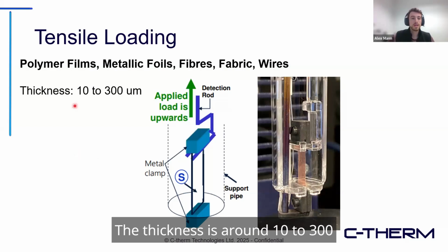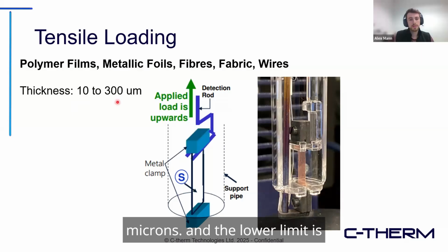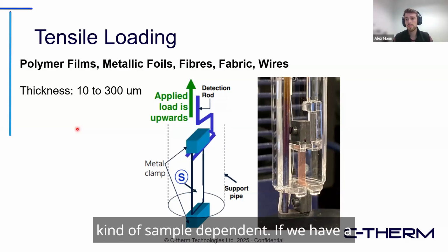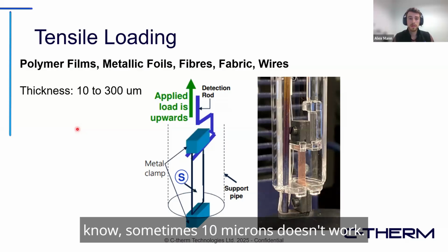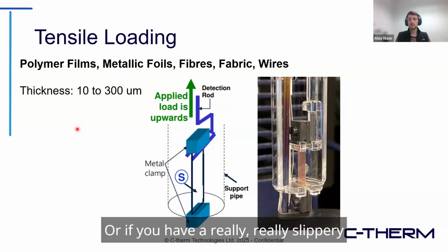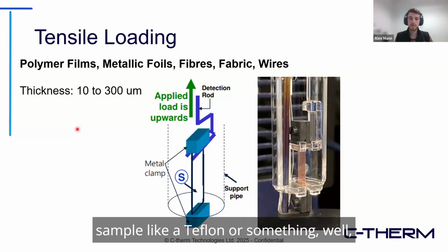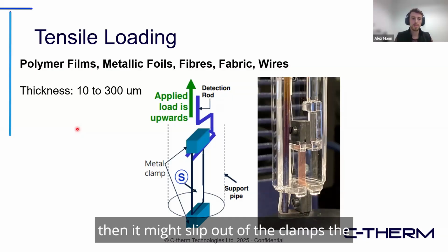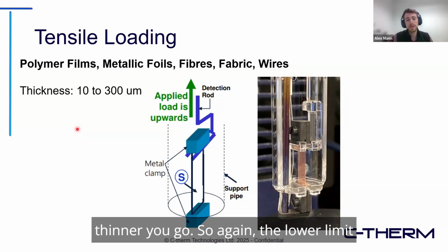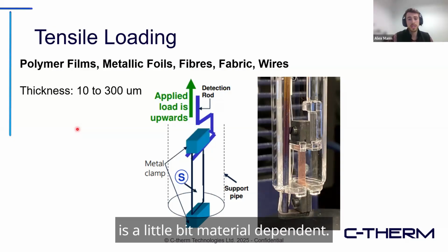The thickness is around 10 to 300 microns. And the lower limit is kind of sample dependent. If we have a very, very weak sample that can't withstand the clamping force, then sometimes 10 microns doesn't work. Or if we have a really, really slippery sample, like Teflon or something, then it might slip out of the clamps the thinner you go. So again, the lower limit is a little bit material dependent.